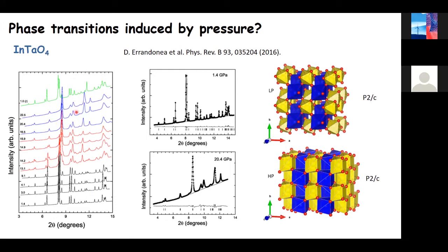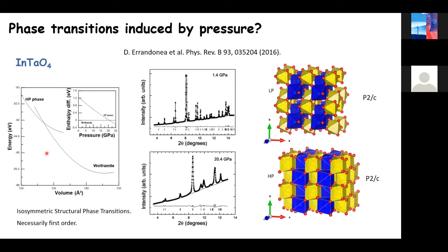We have been working with this pattern, and what we have been able to identify, with the help of the calculations, is the high pressure phase as another monoclinic structure described by the same space group, but different than the previous one. And in this one, we have both cations coordinated with 8 oxygens instead of 6 oxygens. And this will have also important consequences. You can see here the calculation where they predict, both in the enthalpy and in the total energy, a phase transition there and there.